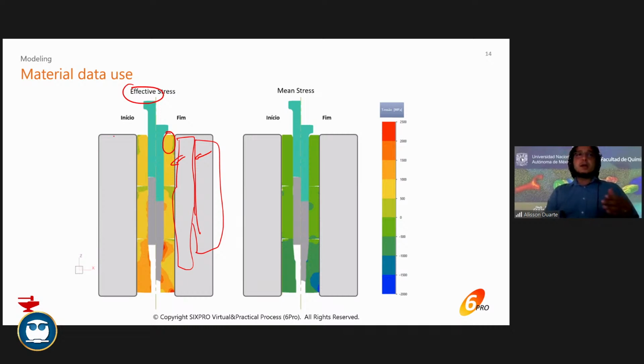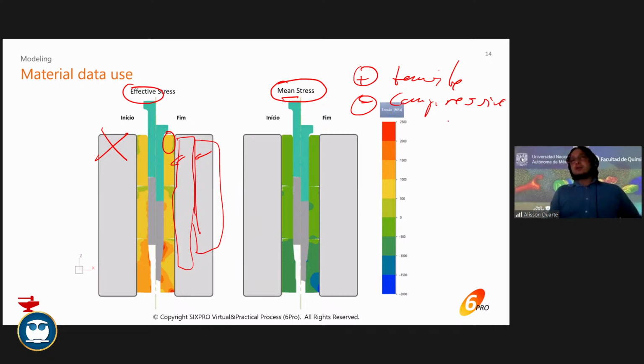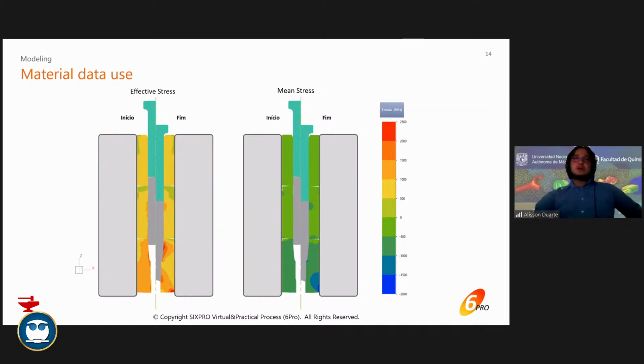It's not shown here because it's a matter of confidentiality. However, you have effective stress here. Another important thing to check is the mean stress, because the mean stress says if we are too much in tension or if we are in compression. So the idea is to get compressive stresses rather than tensile stresses, because they can break the dies. It's very superficial what I'm talking about here, but we have much more, and you can take a look into the dies and analyze them. You can even define the number of blows, the number of parts, until the dies fail or break by fatigue. So there are too many possibilities.